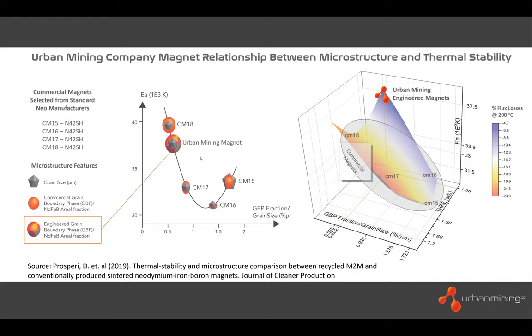What's unique about our grain boundary phase is that it's multi-component, right? We're not using binaries. Everyone else is using binaries. We're using a more finely tuned composition because we have a deeper understanding of the behaviors of certain transition elements combined with rare earth elements that enhance properties efficiently. And that yielded an activation energy that was among the higher activation energies. The higher activation energy you have, the more stable your magnet is at higher temperature, which means you have a better chance for recovering what are called reversible losses. And if you plot that from a compositional standpoint and compare those features against composition, you have a magnet produced by our technology that contains the least amount of heavy rare earth materials with the highest activation energy, or in other words, highest thermal stability than any other magnet that's commercially produced.